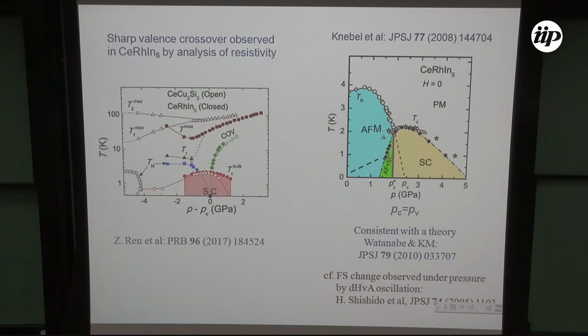This kind of sharp valence crossover is observed not only in CeCu2Si2 and CeCu2Ge2, but also in CeRhIn5. Actually, recently, these people reported on the basis of the analysis of resistivity that the valence crossover lines for CeCu2Si2 and CeRhIn5 almost coincide. That means this pressure corresponds to the valence crossover or valence transition. And also, this is consistent with the theory in this paper, which explains the Fermi surface change observed under pressure by de Haas-van Alphen oscillations, reported in this paper.